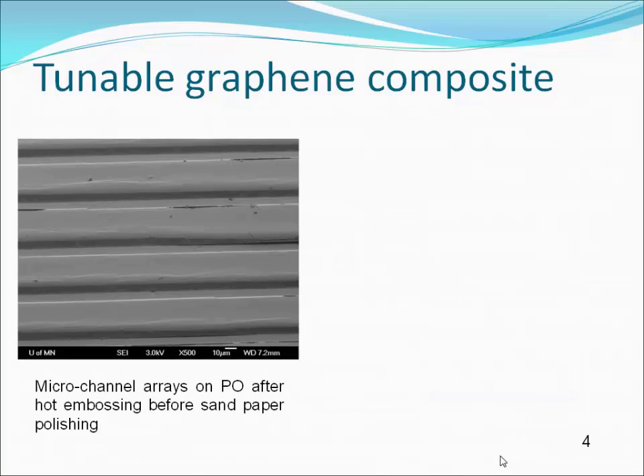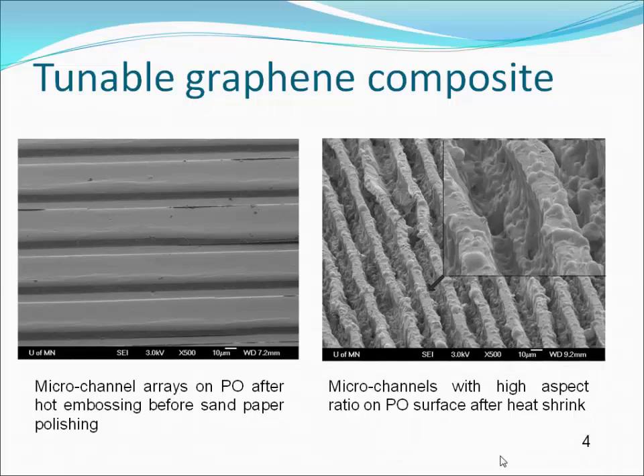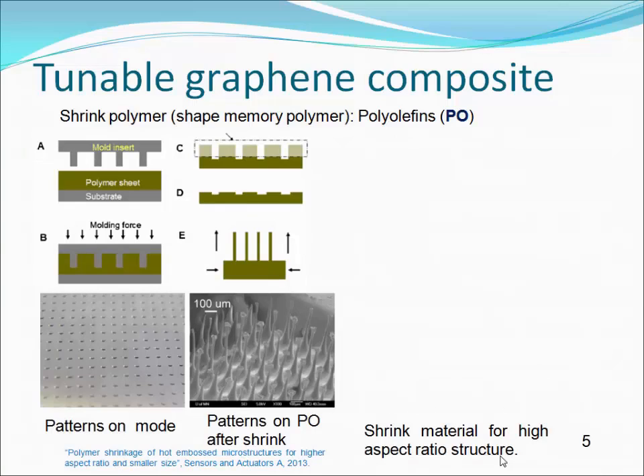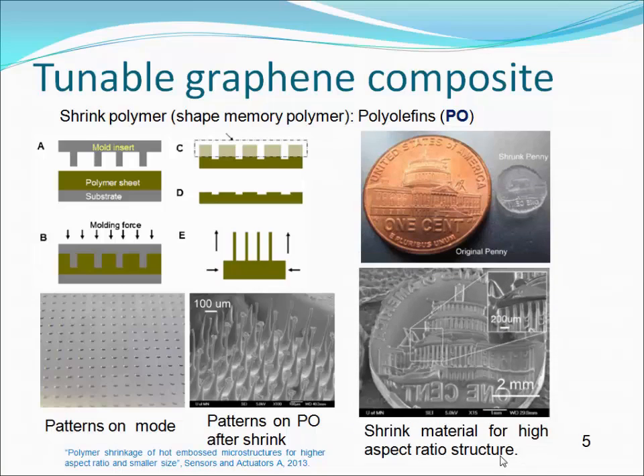This is the SEM of the microchannel arrays on PO polymer right after hot embossing and before sandpaper polishing and heat shrink. And this is the same sample after heat shrink. We can see some microchannels with high aspect ratios on PO surface. With the PO polymer, we can do something interesting. For example, we can change those dot arrays on the mold into the needle shape patterns on PO polymer after heat shrink. We can also shrink the coin into a much smaller size.